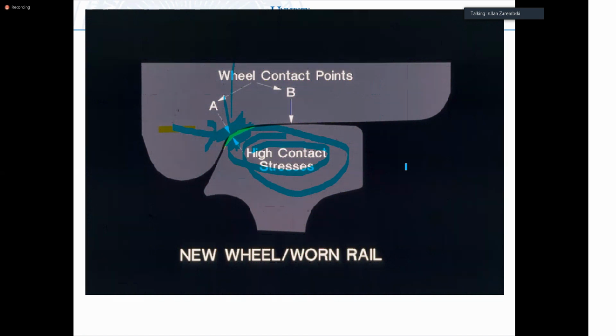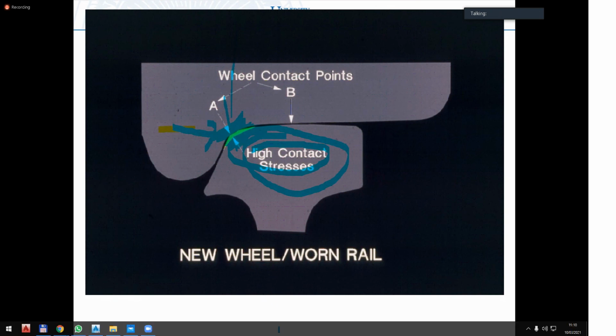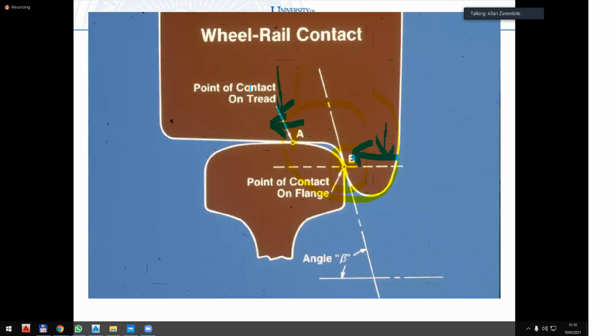So heavy freight railroads do not want one-point contact, because the stresses are so high they're going to generate defects. So they're going to come along and grind the rail. They're actually going to grind off this piece of the rail. We'll talk about rail grinders a little bit, but you saw very briefly a picture of a rail grinder in that Network Rail movie. They're going to grind off that rail and force two-point contact, because by forcing two-point contact, they distribute the load and reduce the level of stresses.